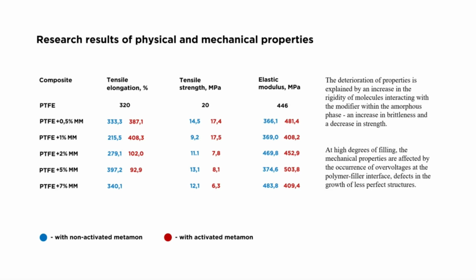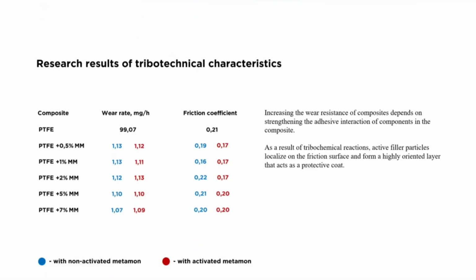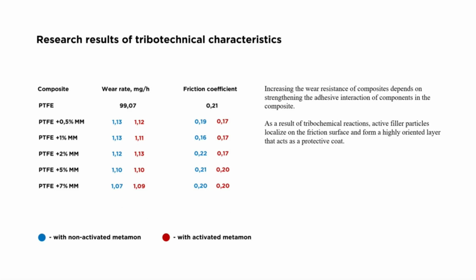As you can see, the tensile strength characteristic of this polymer decreases compared to the initial synthetic fluoropolymer, and depends on the Metamon 101, Metamon 102 concentration. Analysis of the results shows that adding the Metamon 101-102 to a synthetic fluoropolymer leads to a decreased rate of mass wear of the material.